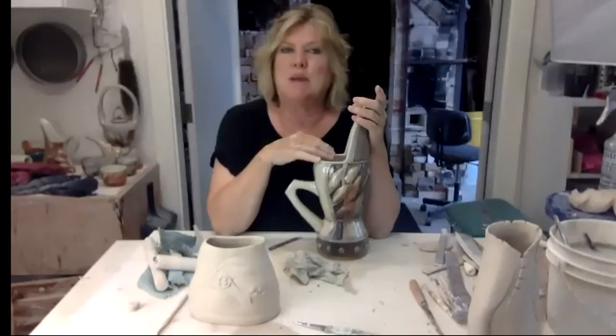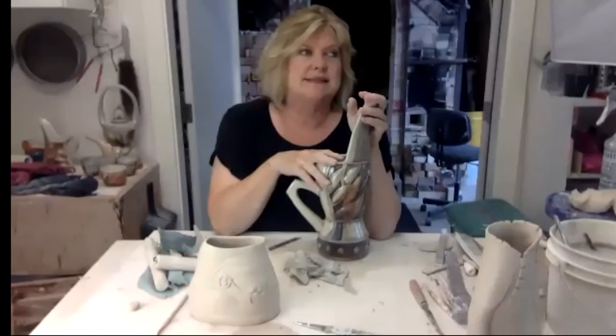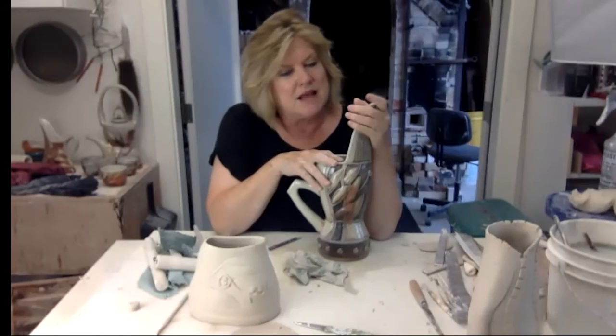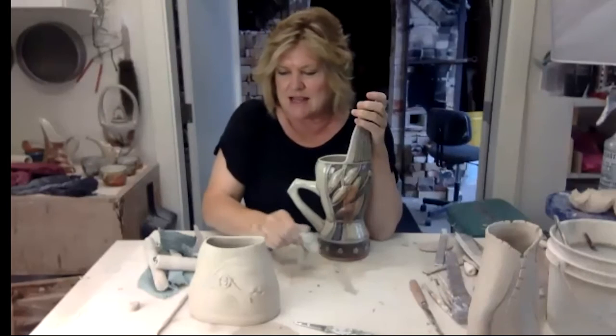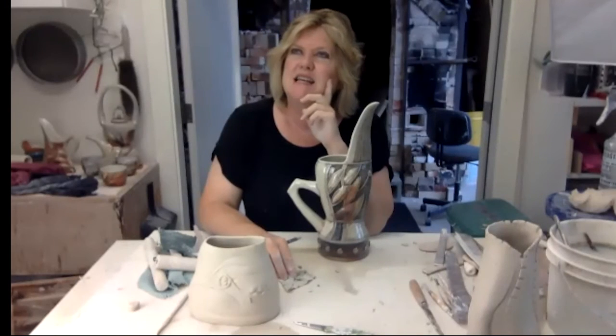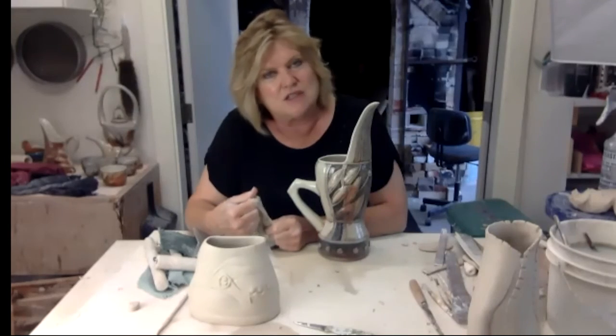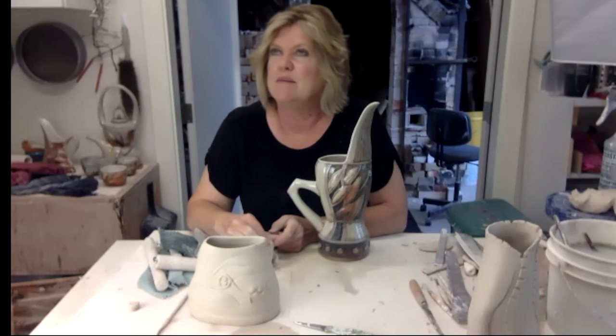Really high iron base, yes. Since you're sharing the kiln with other potters, perhaps they're using something that could possibly flash to your work as well? Yes. I share my kiln with my gallery mates that I help run a little gallery with, and one of them, Mark Moreland, Trackside Gallery. Mark likes to use a lot of commercial cone 10 glazes because he was given them, and without fail they almost always have copper and cobalt, and those will flash on a pot badly next to it.